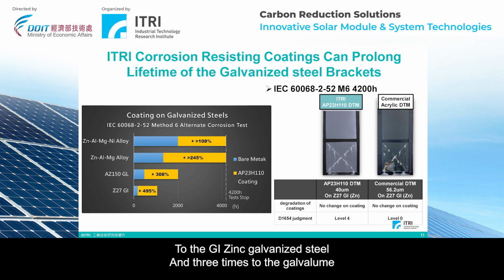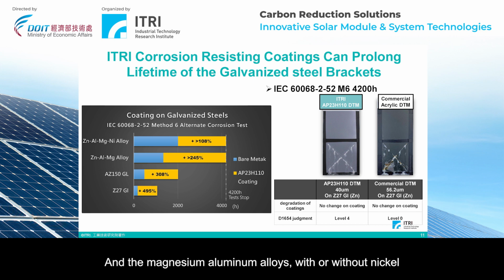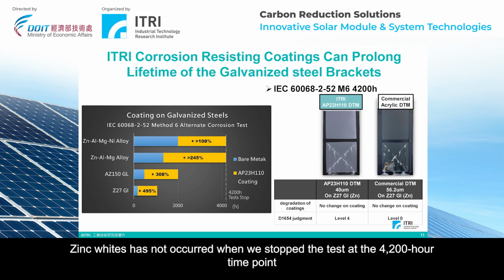galvanized steel, and 3 times to the galvalume, and the magnesium aluminum alloy with or without nickel, all presenting excellent corrosion resisting properties, and even better with AP23H110 DTM applied. Zinc white has not occurred when we stopped the test at the 4,200 hour time point.